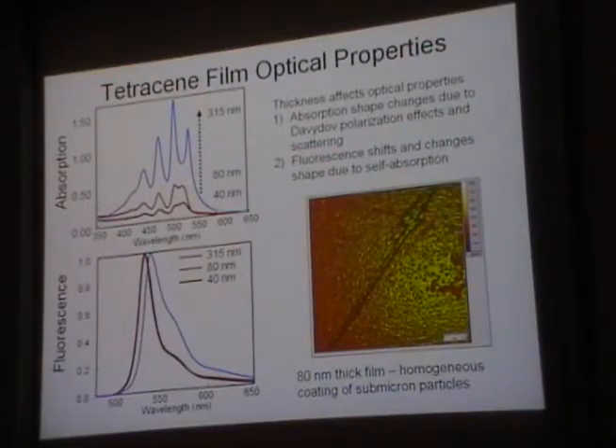So let me just talk briefly about some of the complications of doing spectroscopy on these solid-state materials. There are optical problems. It turns out that if you grow a film of tetracene, and this is also true in pentacene, but you don't see much of it in the literature, you see this weird effect where the absorption shape changes. I definitely don't have time to go into this, but it's an interesting thing. It's because of what's called the Davydov splitting.